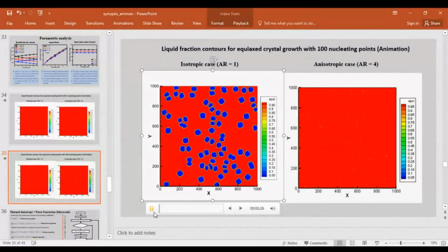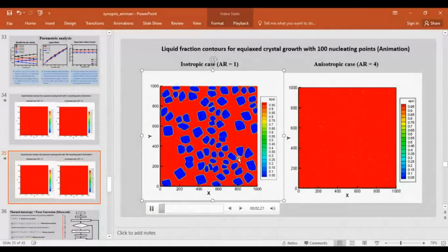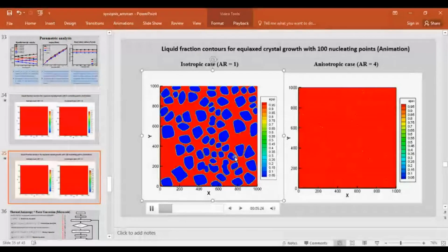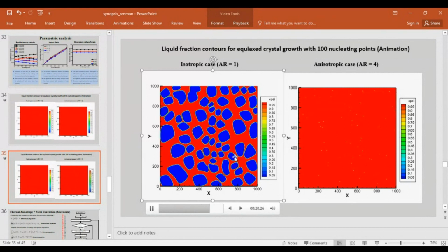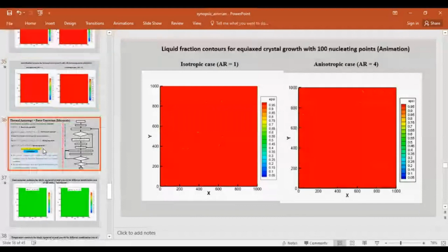Okay, and this one is for the isotropic case. So as you can see, the difference is not much. Based on this, we can see that if the nucleating points are less, then the anisotropy may play a very important role during solidification. But if the number of nucleating points is much more, it may create some problems.